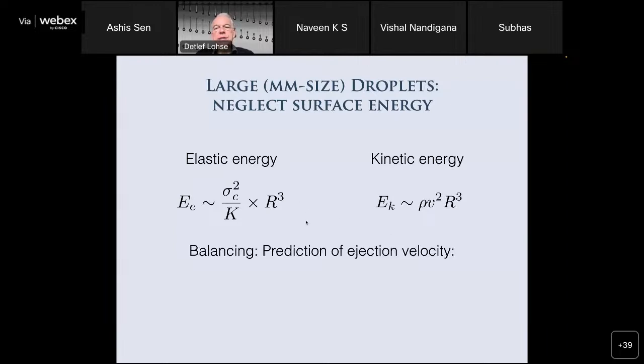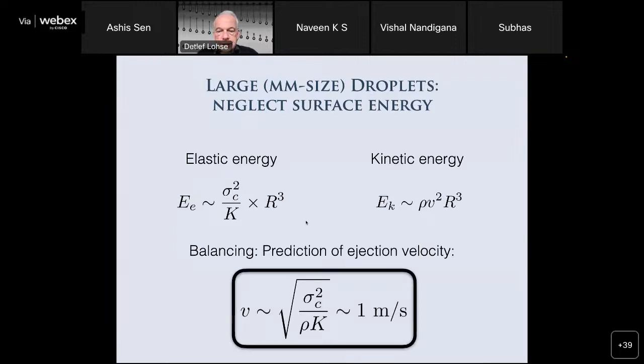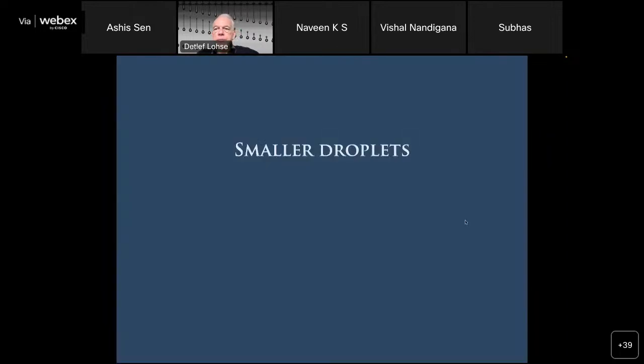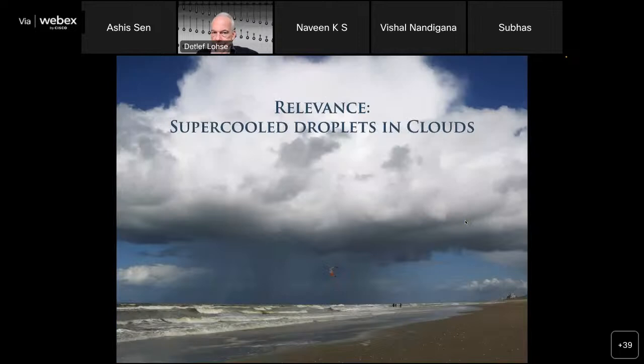And for large droplets, you can neglect the surface energy, and then elastic energy directly goes into kinetic energy. And out of this balance, you can calculate the ejection velocity of these ice particles. And what you get out of this is about 1 meter per second, and this is exactly what we observed, order of magnitude. I mean, it's an order of magnitude estimate, of course, but it works very nicely. So what happens when you go to smaller drops? Well, that's extremely relevant because apparently in clouds, you have these super cool droplets, which are at temperatures -4, -5, -6 degrees. And then what is observed is that all of a sudden, these droplets transfer into ice.